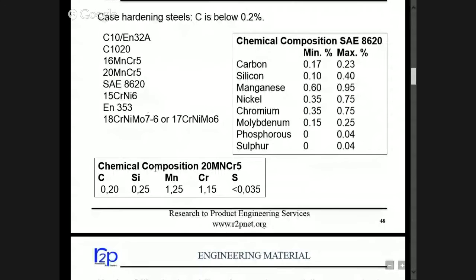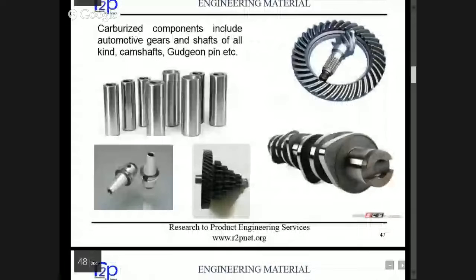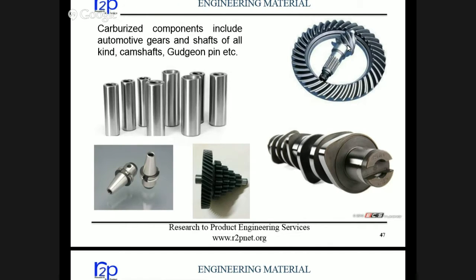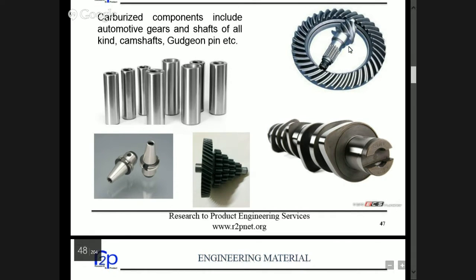In case, if we see in the earlier slide, like in a normal gear which is coming in the gearbox, it's the primary reduction. So the torque here in the primary gear stage is not that high, so we can use 20 MnCr5. But the crown wheel and pinion, since it's being used in the final reduction, here the torque levels are higher. So we will go for 353, which is a better material from the pitting point of view, from the core hardness point of view. So EN353 is generally recommended. And advantages of these alloying elements we will see.